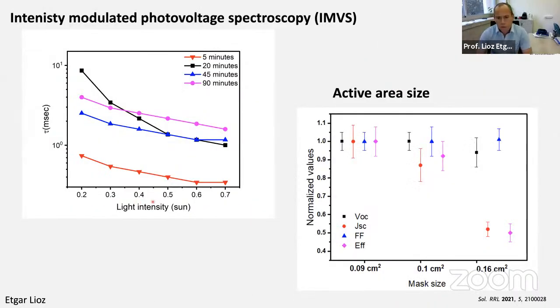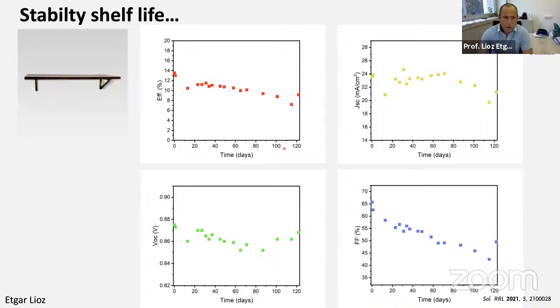We also performed measurements with different active areas for those devices to show that they are really not affected by the device area. And finally, we move to the stability. With those carbon cells, the main advantage comes from their stability, due to the carbon layer on top that coats the device. If we start with the shelf-life stability, you can see nicely that this is days, not even hours, that it's quite stable. It's still not optimum, but we also have to understand that we are talking about unencapsulated devices outside, and this is something nice.